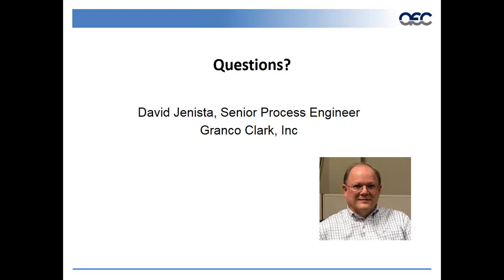It then requires artificial age to reach either T5 or T6. If you don't put it in an artificial age environment, it will, over a period of weeks, reach T4, but you will not be able to make T5 or T6 properties without the artificial age step. And what I may have said is that it's possible to get to T6, or I intended to say it's possible to get to T6 using press quench. Not that it is T6 as it exits the quench. And if I said that, I misspoke.